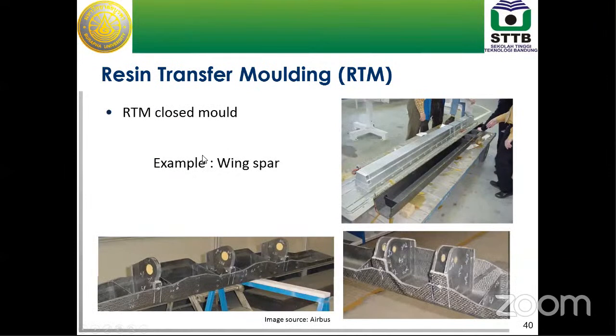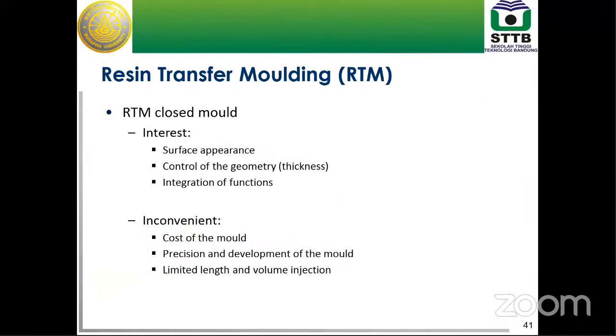And I give you some examples of parts. In this slide, you can see a wing spar for aircraft made by RTM. You can see the shape, it's very complex. You have different thicknesses, a lot of curves, a lot of shapes. So you can create very complex parts. The advantage of this process is the quality of the surface is pretty good. You control the geometry, and the thickness of your part is well controlled. And you can integrate functions in your preform. When you create the preform, the shape with the fiber, before the resin, you can already install some functions. If you want some metallic part to reinforce some place, you can already insert your reinforcement.